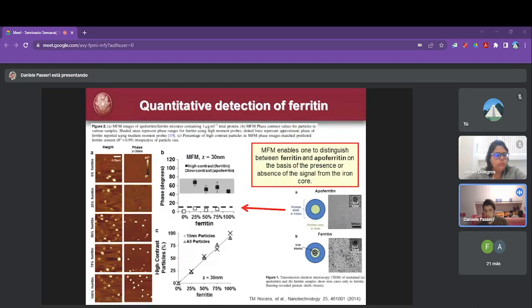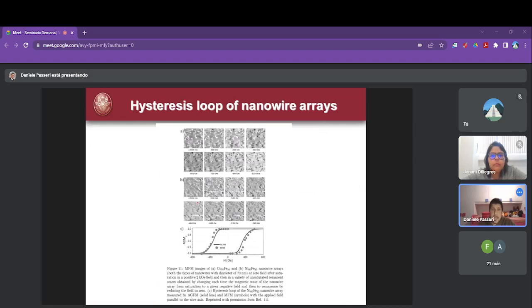So this very low phase shift corresponds to apoferritin, so without the iron core, while this higher contrast is the ferritin, and this higher phase shift is due to the iron content. Another nice result, which is not from a biological system, of course, is this result, which is